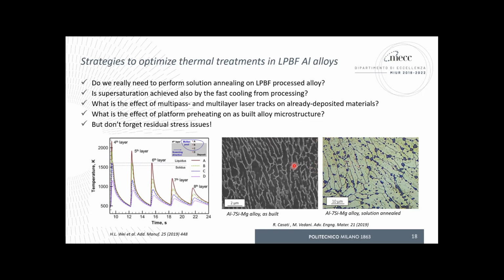Indeed, we can consider these two micrographs right here. On the left side, we have an aluminum 7% silicon alloy in as-built condition. We already had the chance to talk about the very fine microstructure, very nice. While on the right side, we have the same alloy after solution annealing, so holding the alloy at 540 degrees C for a couple of hours. The grains coarsen very much. Please consider that the labels here are different. Okay, they coarsen very much. We have larger precipitates. So it's really a pity, in my opinion, to spoil, to remove this very nice fine microstructure.